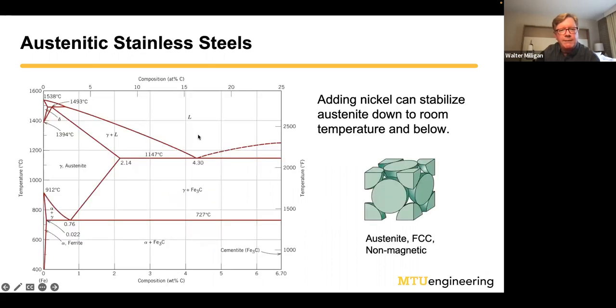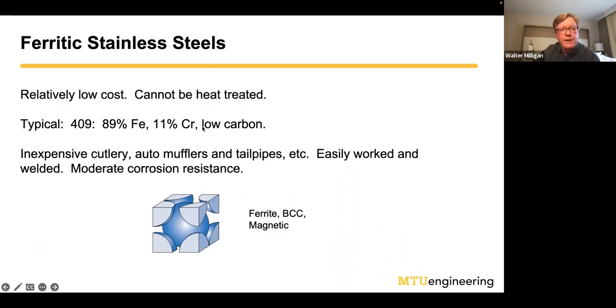One of the big advances in mufflers and tailpipes, I'm old enough to remember cars from the 70s where you had to get a new muffler and a new tailpipe about every year and a half because they turn into a pile of rust. And they started making those out of 409, and now they'll last 10 or 12 years. So they have pretty good oxidation resistance. They're also good if you need to weld something because you can weld them. The martensitic steels, you have trouble welding because of the heat treatment issues after that. They have moderate corrosion resistance. And so they have the body-centered cubic structure, which is the ferrite phase in the phase diagram. I'll show that diagram in a second again, and they're very magnetic.